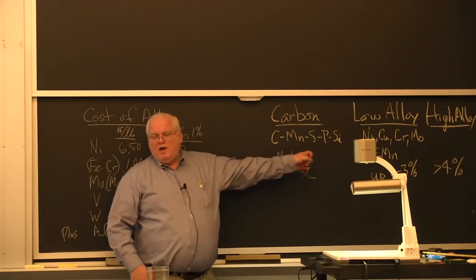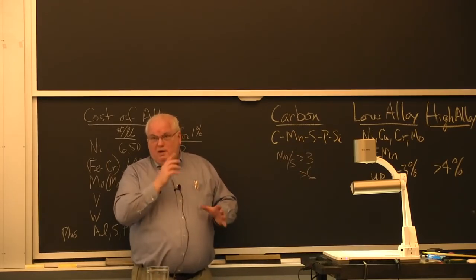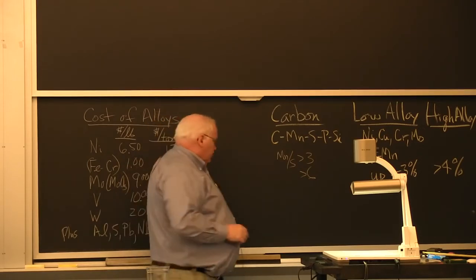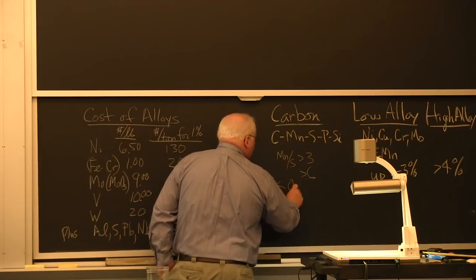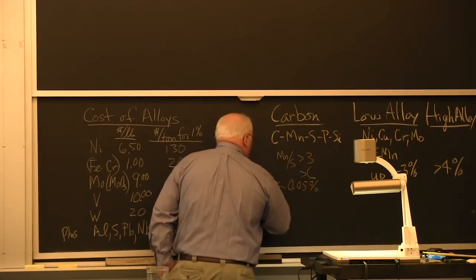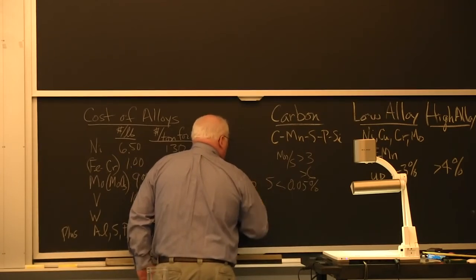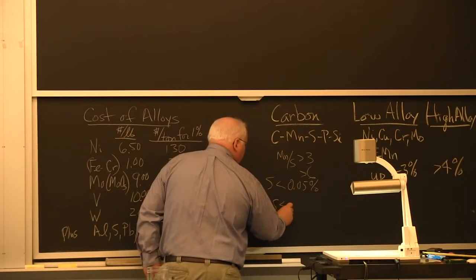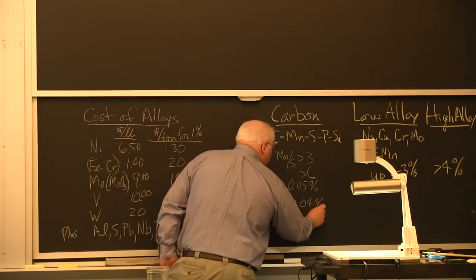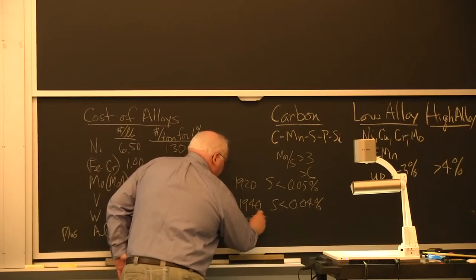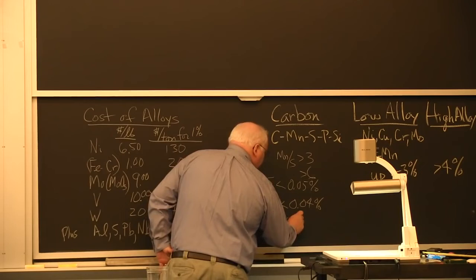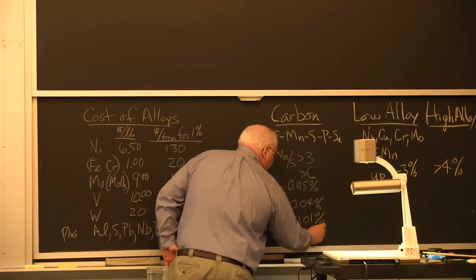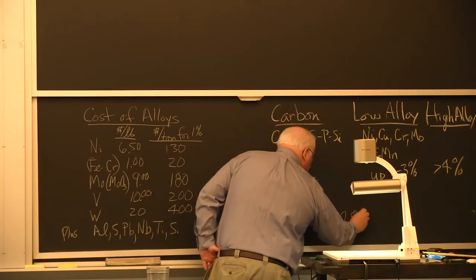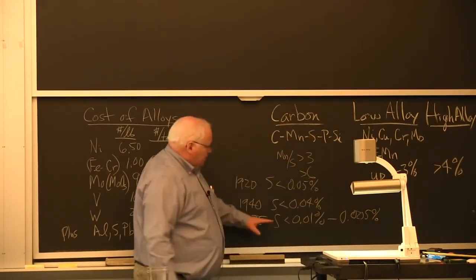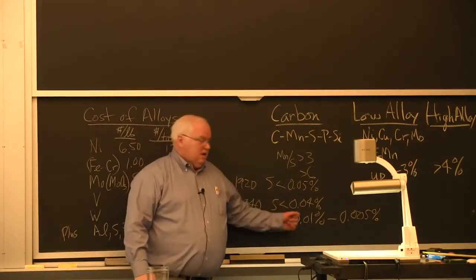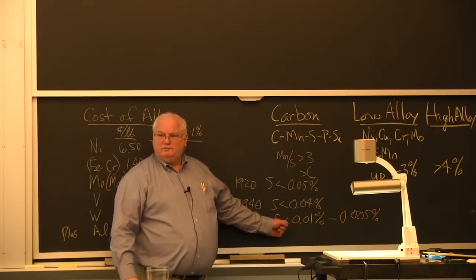Okay? If I go look at an ASTM spec that was originally written in the 1920s or 1930s, it will say the sulfur must be less than 0.05%. And so that's, let's say, 1920s. And by the 1940s, they were saying the sulfur must be less than 0.04%. Okay? By 1975, when Tom Eager was working for a steel company, the sulfur was typically less than 0.01%, and the Japanese were making it at 0.005%. Okay? They had modern equipment, and they were beating our socks off in quality of steel. So you want to have the sulfur very low in almost every case.